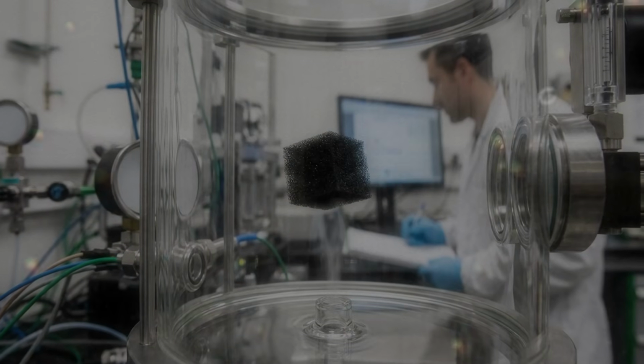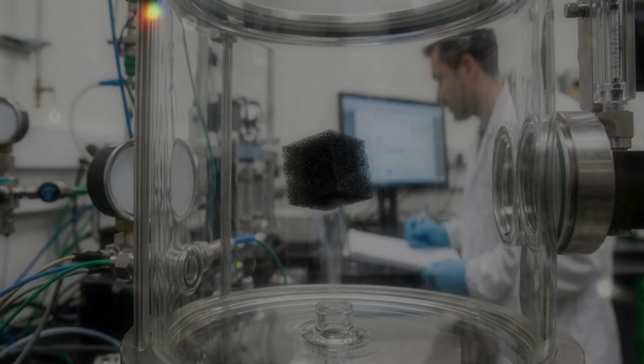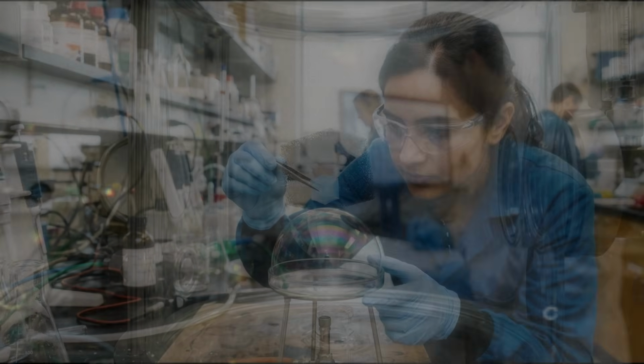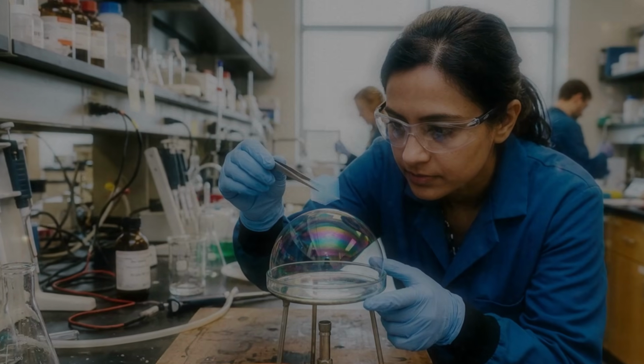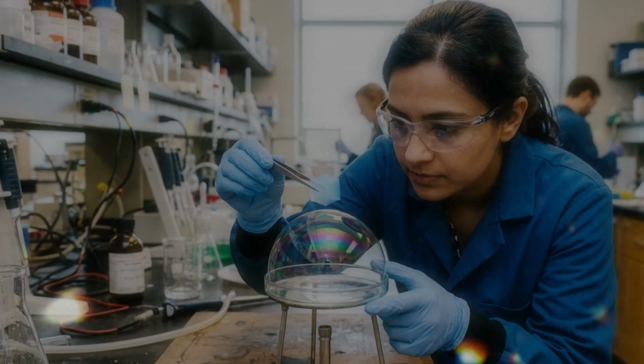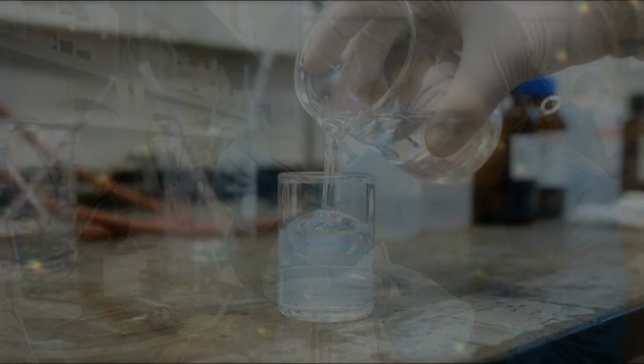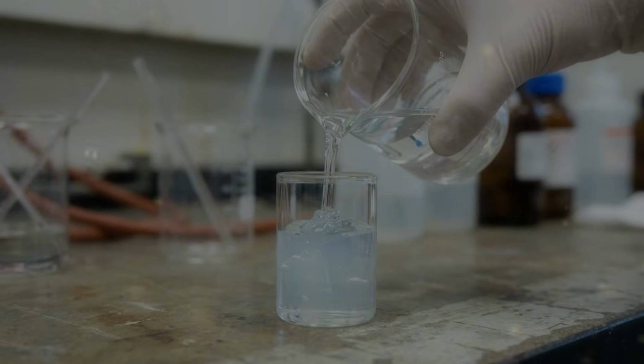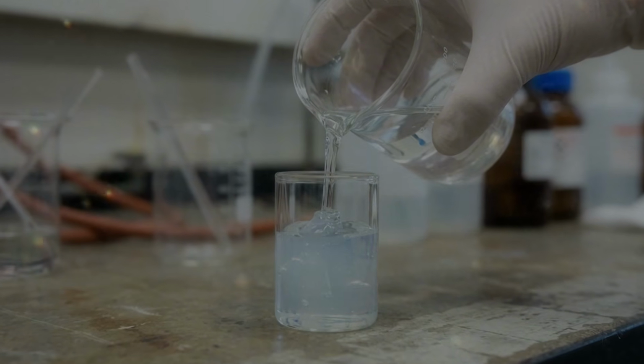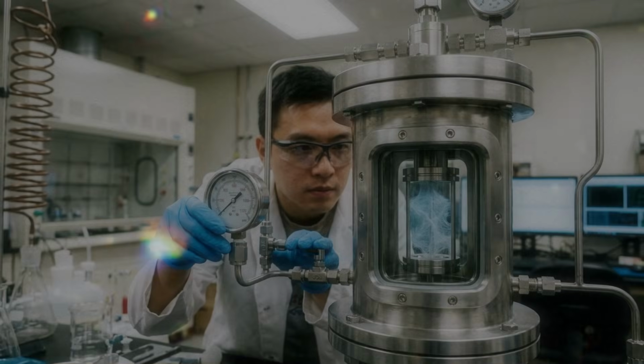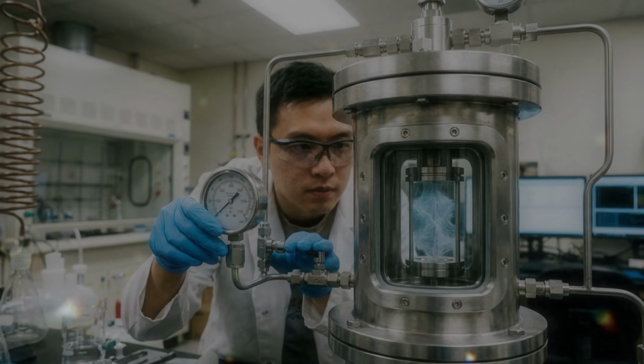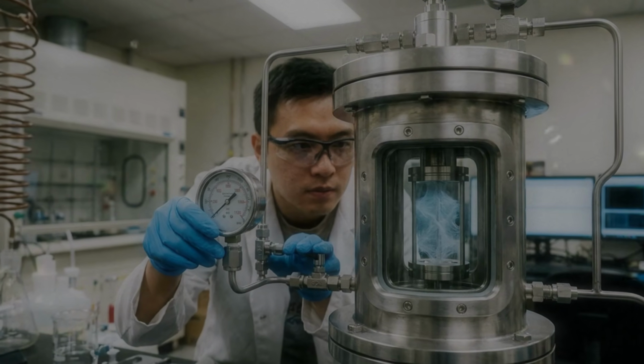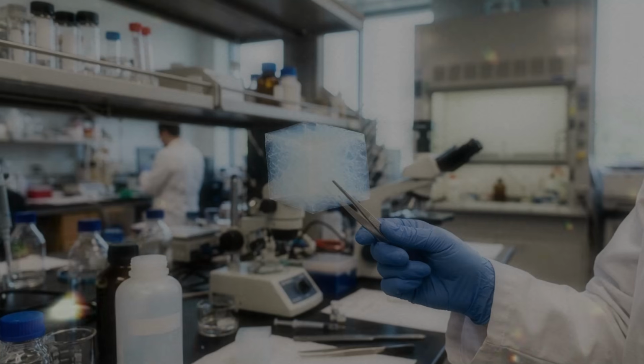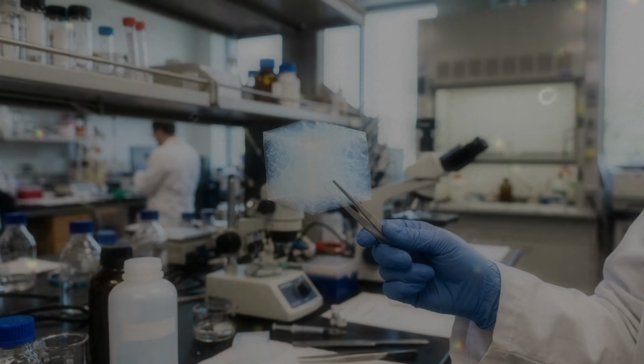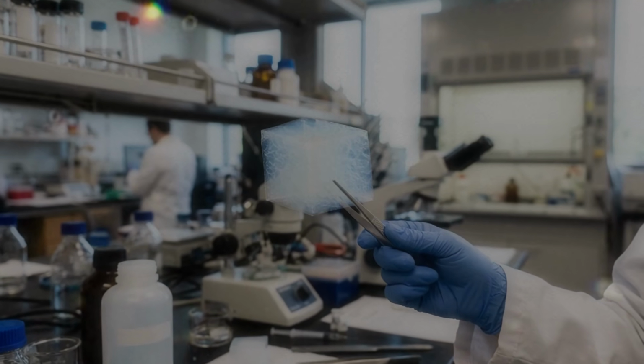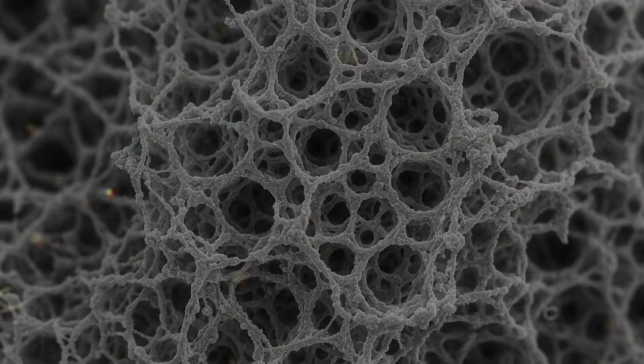The gas inside the pores also carries little heat because the spaces are small. Gas molecules cannot travel far before meeting a wall. They repeatedly collide with the internal structure, limiting the distance over which they can transfer energy. Larger pores can allow more gas movement. If the spaces become large enough, circulation may begin and insulation performance can fall. Very small pores help suppress this motion, but they may also make it harder for liquids to move through the material. The ideal pore size depends on what the aerogel is meant to do.